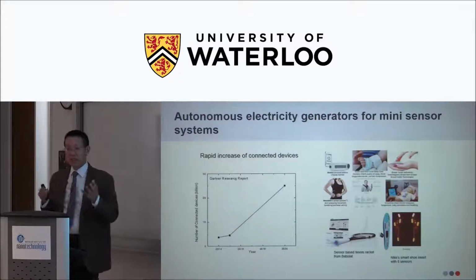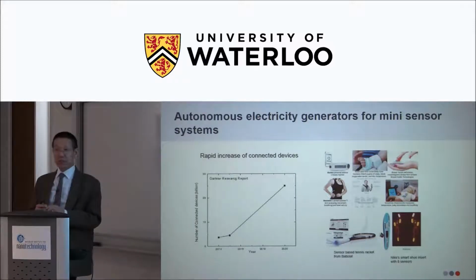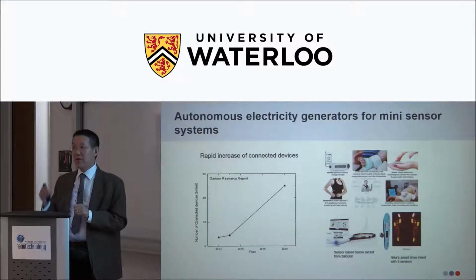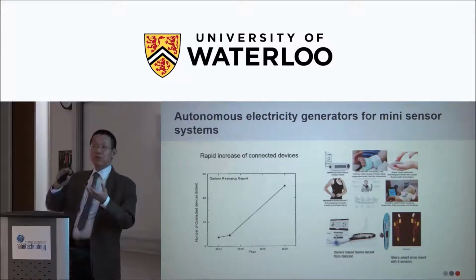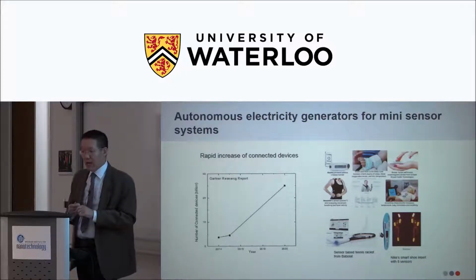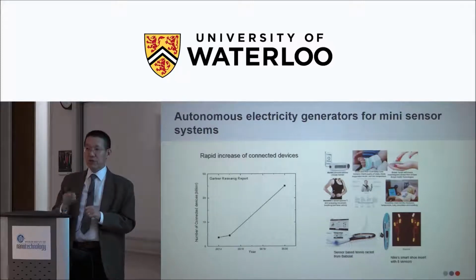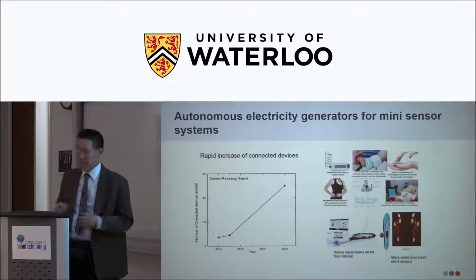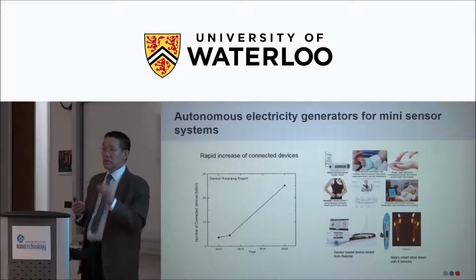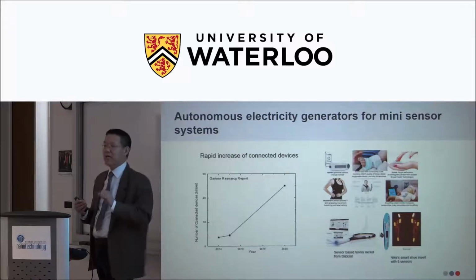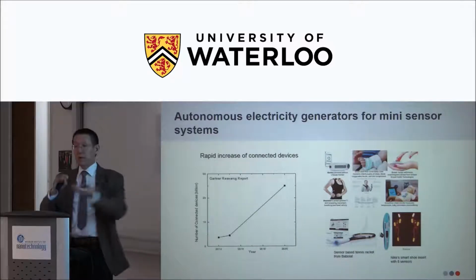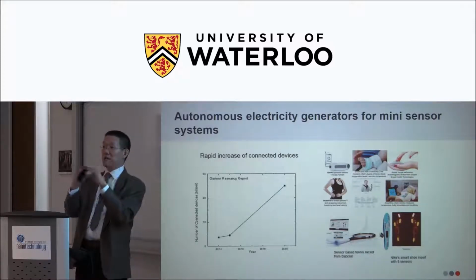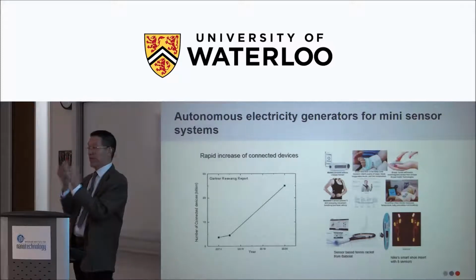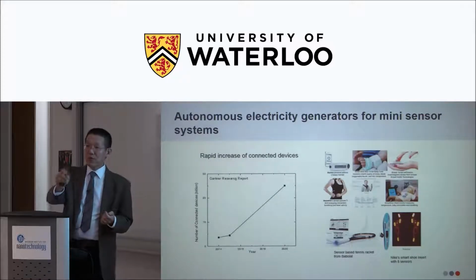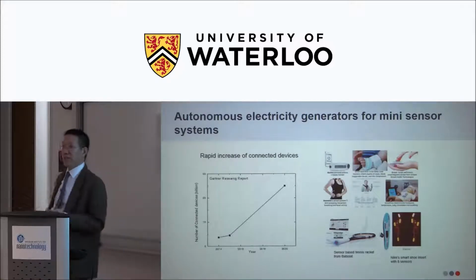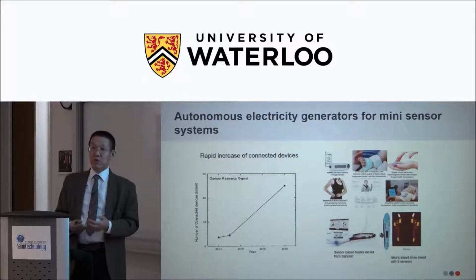One application we think will be interesting is the energy harvesting area. A lot of energy harvesting devices need to be flexible and mechanically foldable. The energy generation is typically proportional to the device area, so you need a large area. And in a lot of cases, you don't mind the performance of each individual action. For example, I'll show you a piezoelectric device. When you fold it, you generate 50 microwatts. Next time you fold it again, you get 40 microwatts. Who cares? Because you want to integrate this into a capacitor and use the average output later on. So you have very large tolerance towards those errors.